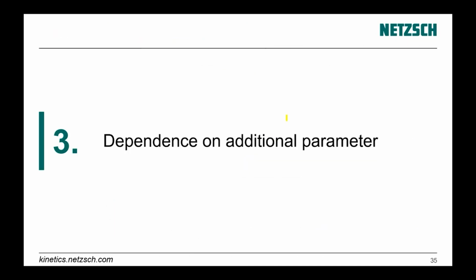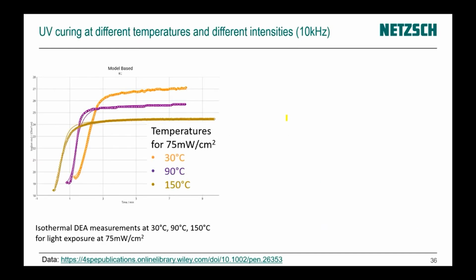And now a very nice part is the dependence on an additional parameter. Here we speak about UV curing, the curing under UV light. The measurements are done with dielectric analysis at a frequency of 10 kilohertz. We make a measurement for one constant value of UV intensity, 75 milliwatt per square centimeter, at temperatures from 30 to 150 degrees C. And we have some model.